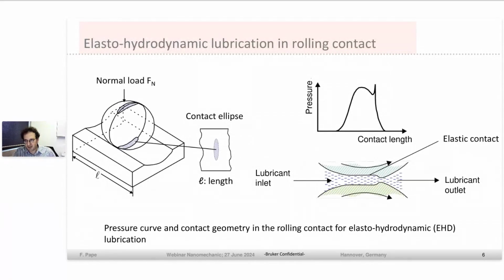But back to the basics, we have to understand at first that we have very high load in the bearings. On the left, we can see a ball running on the raceway. We have a normal load and a resulting contact ellipse, as we have a Hertzian contact stress. You can see on the right the lubricant inlet zone, and we have an elastic deformation of the ball and the raceway itself, and a high pressure in this zone. Additionally, also an increase in temperature. And under these conditions, the lubricant forms tribofilms, which are glassy-like.